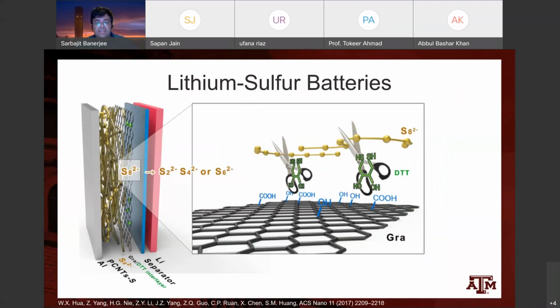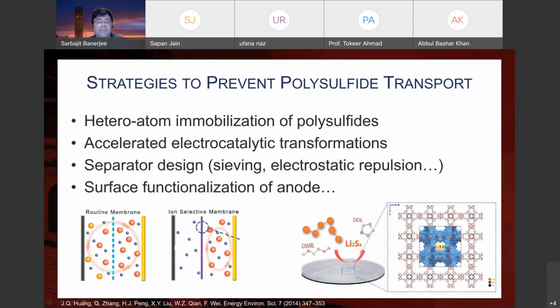There are a lot of different strategies that are being unveiled to essentially prevent this polysulfide dissolution and shuttling problem. Part of this idea is to have some heteroatoms like nitrogen atoms and such in the carbon lattice that can interact with the polysulfides. Another idea is to use separators that are ion selective membranes that allow, for instance, transport of lithium ions, but prevent these polysulfides from going across.